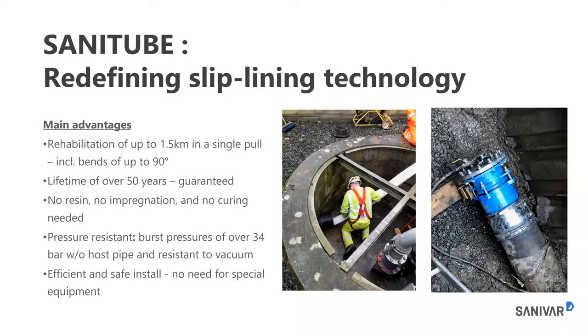A lifetime of over 50 years is guaranteed, and it's been tested under laboratory conditions to verify that. And as I say, we actually have 30 years of provenance in the field around Europe on potable water mains. I've already alluded to the fact that there's no resin or impregnation or curing time, so it's very quick to install. It's pressure resistant, both positive and negative pressures. It's capable of burst pressures of over 34 bar without a host pipe, and it is resistant to vacuums.